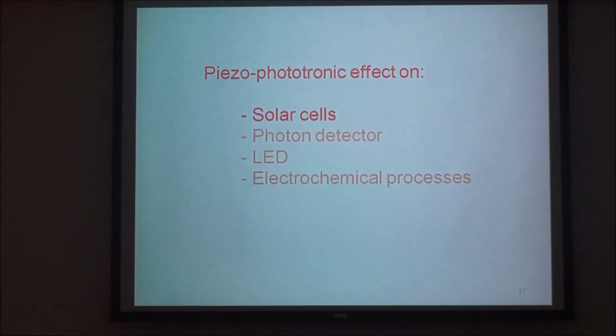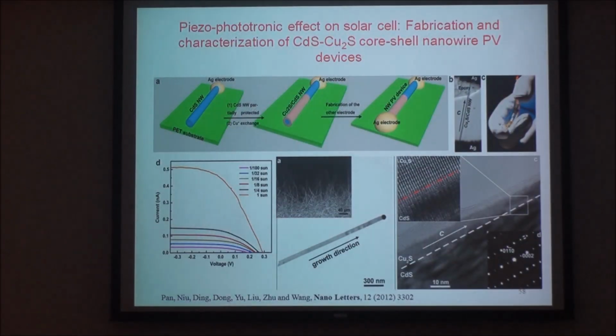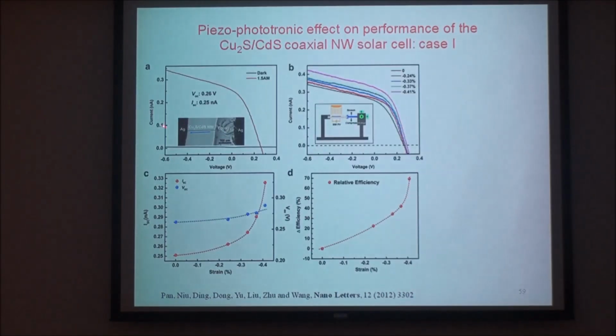First one is the solar cell. If you use a single cadmium sulfide nanowire with copper sulfide as the shell, this is the P type, this is the N type, a p-n junction, core-shell. And we use microscopy to prove it is the case. If this is the solar cell, if you measure the solar cell performance, you get this. It's not the best solar cell at all, but I want to show the effect.